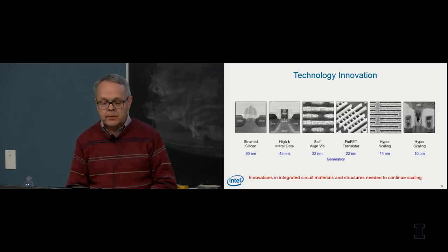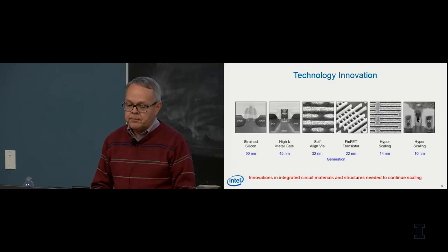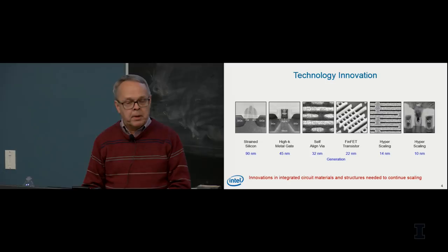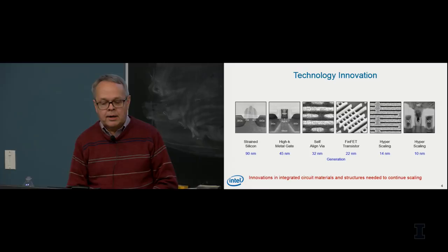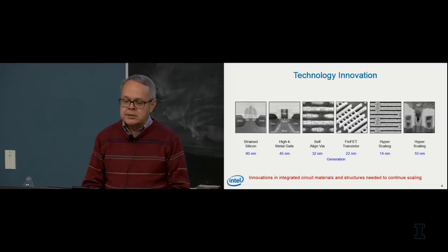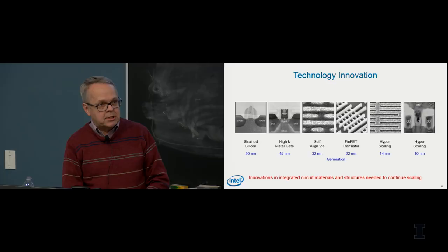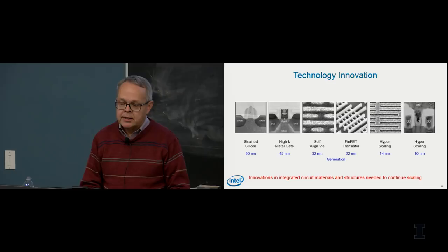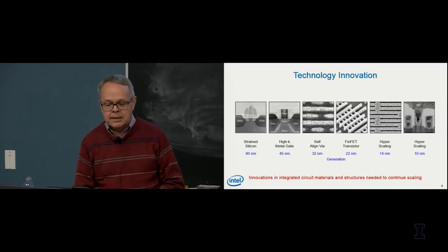The next big change was our high-k metal gate technology, where we changed the gate insulator from SiO2 to a hafnium-based high-k material and replaced the doped polysilicon gate electrode with special metal materials to provide the right work function. We also started to pay attention to interconnects — interconnect scaling is just as important to microprocessors as transistor scaling — so we invented something called self-aligned vias to make sure all vias and metal wires would be in place, especially important at very small dimensions.